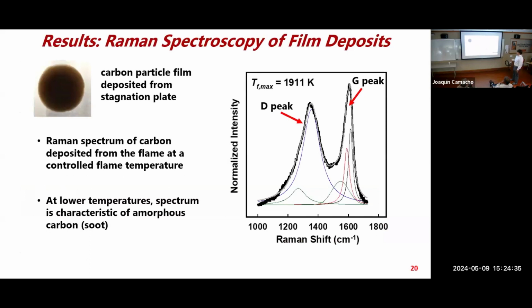Here is a Raman spectrum of this film. It takes time because at these high temperatures, there's not a lot of soot yield, so it takes time for this film to grow to get a signal from it. This is taking a film and putting it under the Raman spectrometer. This is the signature we get.